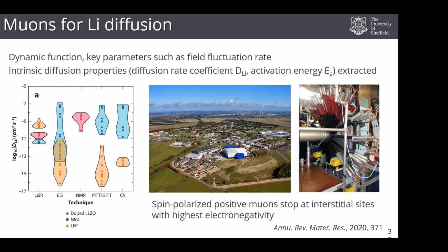What we do is we embed these muons into our material, and they sit within the material and act almost like a lighthouse. They're looking around at what's happening. And because they have a spin, anything that moves nearby can change the orientation of that spin. So if a lithium ion moves nearby, that spin can change. And what happens is after about 2 microseconds, the muon decays and it emits something called a positron in the direction the spin was pointing just before the muon decayed.